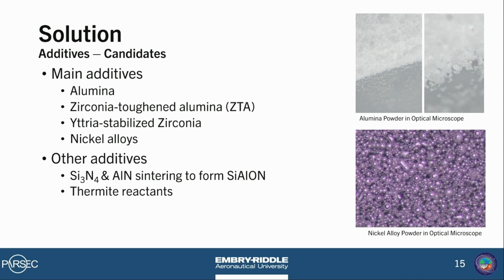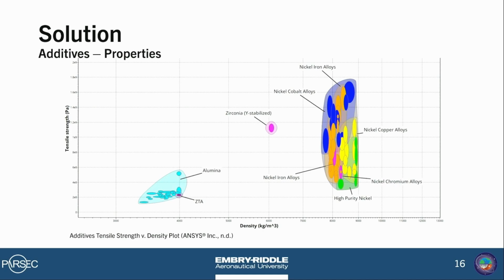about shortly. There's also a couple other additives that we do mention in our technical report. However, we won't be mentioning them in this presentation for the sake of time, and also because they involve processes a little more complex and different from thermal spraying, and we have not assessed their viability to the same extent. However, if you are curious about any of these additives, feel free to ask us during our poster session. So here is a plot of tensile strength versus density for our main additive candidates that we obtained using the ANSYS Granta Selector database. Using plots like this, we're able to make some very rough comparisons between our main additive candidates to determine various strengths and weaknesses among each.